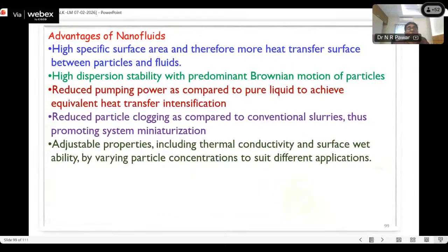And these are some advantages of the nanofluid, because these nanofluids have high specific surface area and therefore more heat transfer surface between the particle and the fluid, high dispersion stability with predominant Brownian motion of the particles, reduced pumping power as compared to pure liquid to achieve equivalent heat transfer intensification, reduced particle clogging as compared to conventional slurries, thus promoting system miniaturization, and adjustable properties including thermal conductivity and surface wettability by varying particle concentration to suit different applications.